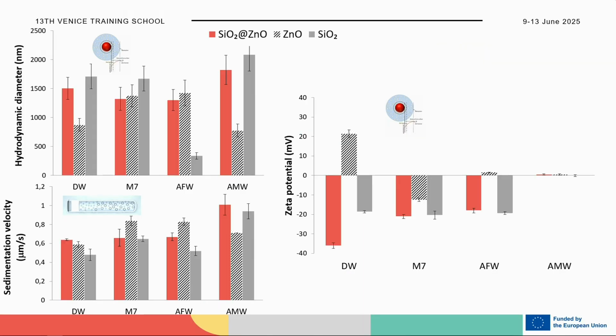So what we did basically, we compared the dispersion stability of the advanced material with the precursors, I would say, so the zinc oxide and the silica dioxide, by increasing the complexity of our media, so moving from the deionized water and then to fresh water, that is this one. Then M7 is quite more close to fresh water and is used for testing Daphnia magna. And then we move lastly to artificial marine water.